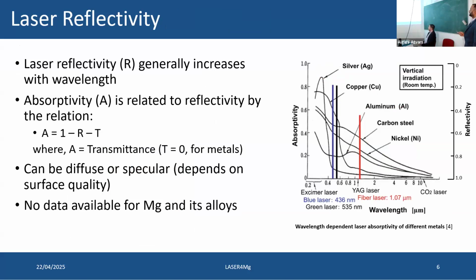Reflectivity values for some of the common metals are shown here. This is the infrared wavelength, and the absorbability is about 20% for aluminum. Nickel is slightly higher. Steels have much higher than that. There's a general trend that as the wavelength increases, the absorbability basically decreases, and that makes it very difficult for the entire system to be efficient. Such a study has not been performed for magnesium alloys, which in recent years are gaining a lot of ground with material scientists and designers.